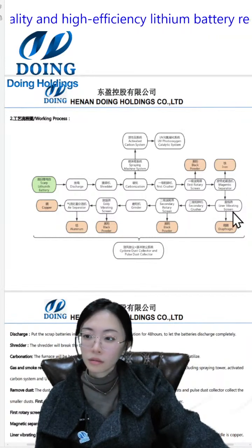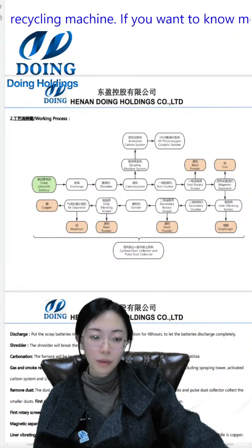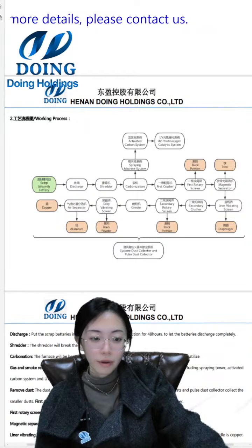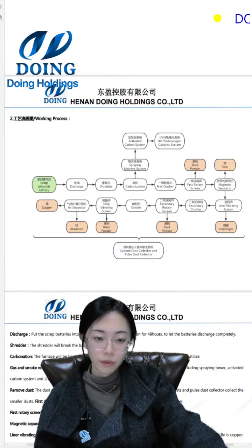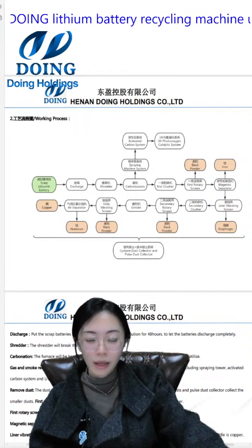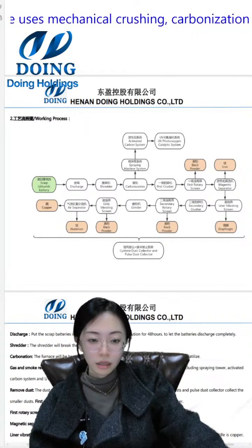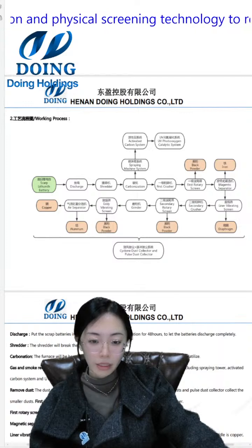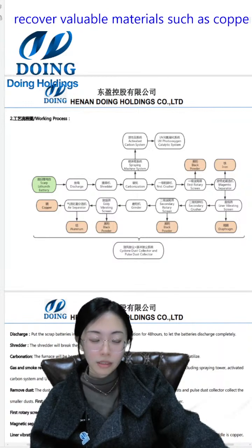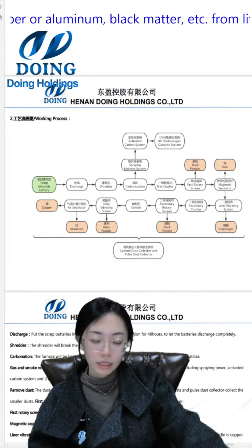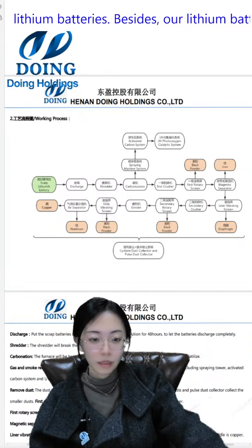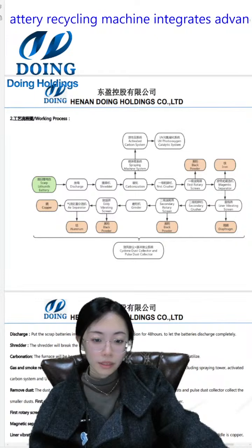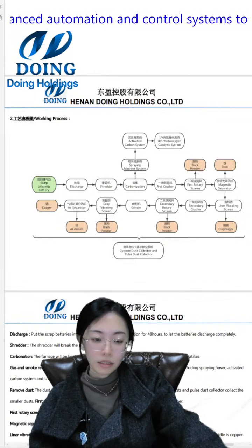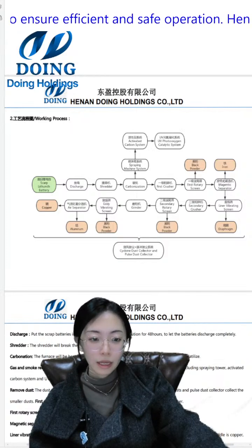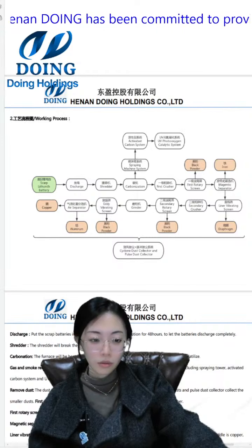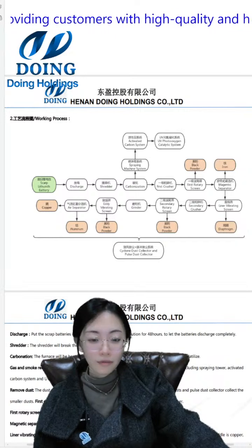And then the material will go into the linear vibrating screen. It uses the vibration of the screening, and different products are controlled by the multi-layer screen and discharged from their respective outlets. The two-layer screen is 2 millimeter and 100 mesh, a stainless steel wire mesh. The top layer of the screen is the diaphragm, so in this step we will collect all the diaphragm and recycle it. The second layer is the copper, aluminium, and some black powder. And the bottom layer is all the black powder. So this is the linear vibrating screen.